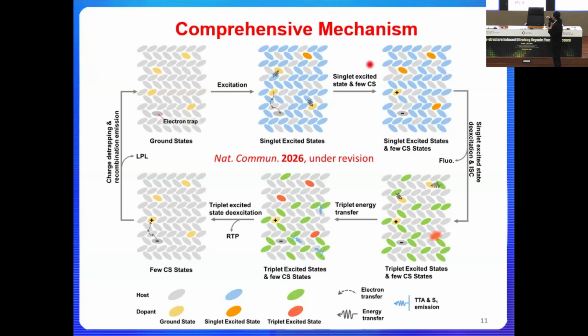All right. And in the next step, the excited state can go back to give fluorescence. That's one pathway. And then the triplet state can also undergo energy transfer to the guest molecules. Then you will observe the phosphorescent emission from the guest. And the rest of the triplet state from the host may also go down by themselves, so that you are expecting room temperature phosphorescence from the host. Depending on the energy levels between the host and guest, you may only be able to observe phosphorescent emission from the guest, or you may be able to obtain both from the guest and the host.